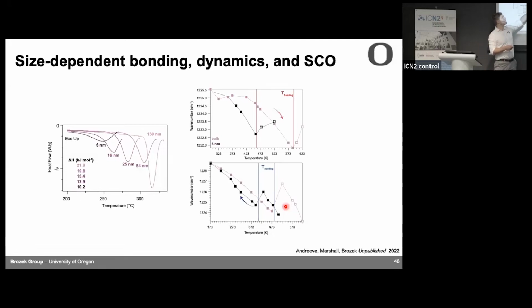Everywhere you see a dip in the data, that's where the spin crossover happens. And we see that for the smaller particles, the spin crossover happens at lower temperatures. And so we can really control that over 50 or 100 degrees just by changing the size of the particles. We also see that in the IR data. So we see that they redshift for the different sizes, but the redshift is steeper, more temperature dependent, for the smaller particles. So this is all nice.